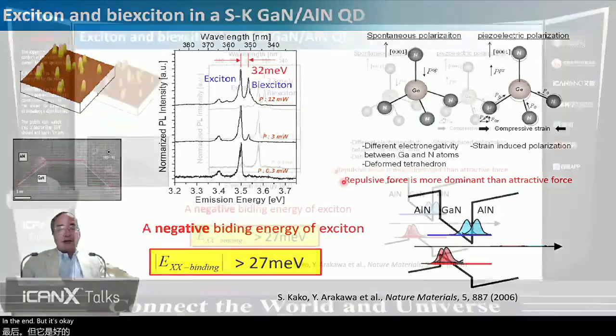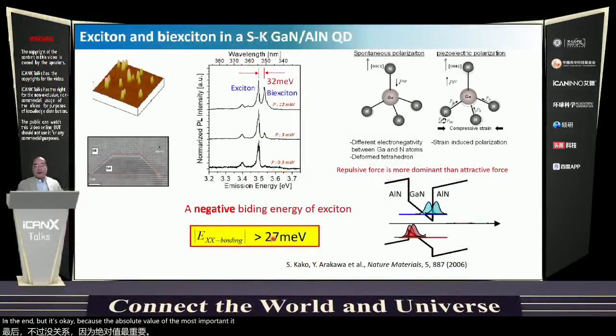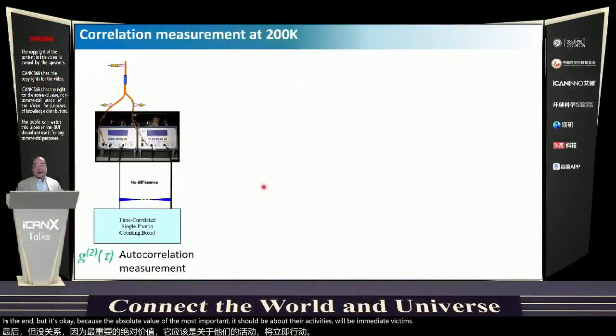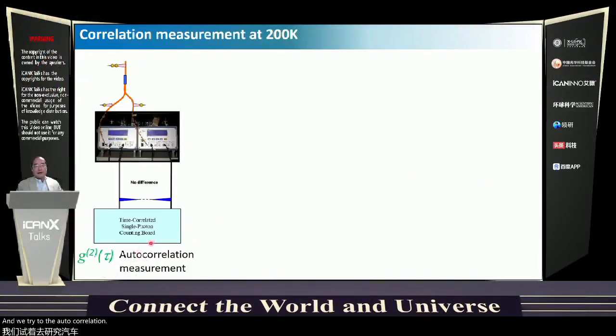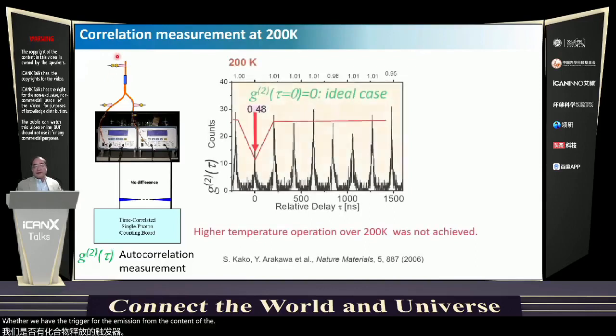But it's okay because absolute value is the most important. It should be larger than 27 milli-electron volt. And we try the autocorrelation measurement for checking whether we have single photon emission from the quantum dot structure. This is an experimental result, and in the ideal case, at the delay time of 0, the value called g2(0) should be equal to 0. However, if this is smaller than 0.5, it's okay.